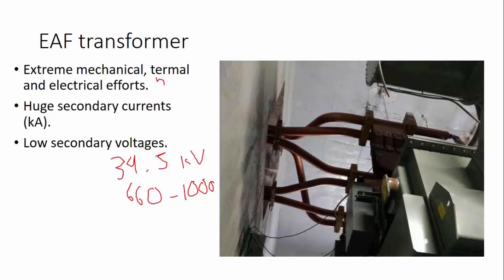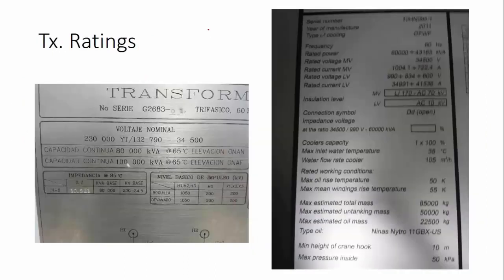As you can notice, the secondary of this transformer connects to the oven not by cables but by copper buses, which are also water cooled. It's a lot of current. So as you can see, this is the main furnace transformer, which is up there in the substation. This is a 230 kilovolts to 34.5, and it's an 100 MVA, a very big transformer.